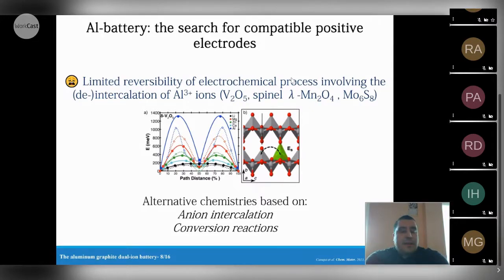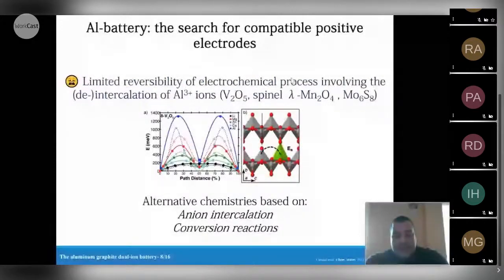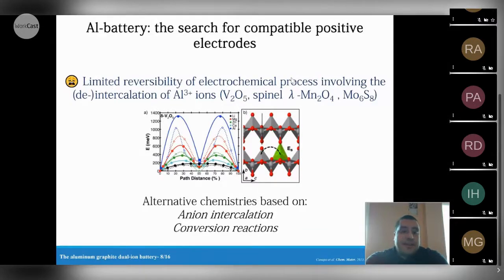The second main issue is related to the identification of a suitable positive electrode. And the main limitation in this case is associated with the high charge density of the aluminum ion and the limited mobility of the aluminum ion in metal oxide framework. This is, for example, a comparison of the diffusion energy required for the different ions, lithium, magnesium, zinc, calcium, and aluminum, to move in a metal oxide framework. In this case, it is a vanadium oxide. And we can clearly see that for aluminum, the energy required is extremely high, making it unsuitable for battery application.